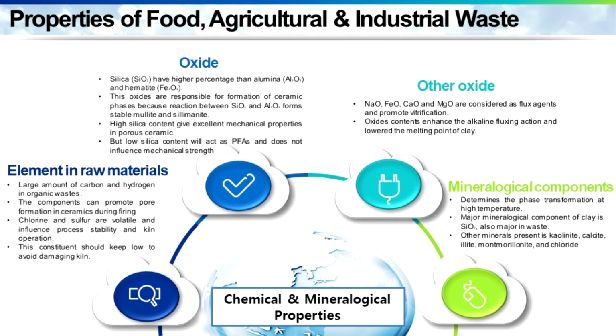For instance, the major silicon dioxide and aluminum oxide will contribute to the siliceous properties of the waste. These oxides are responsible for the formation of ceramic phases because the reactions between the silicon dioxide and aluminum oxide form stable mullite and sillimanite phases. These reactions result in porous ceramic with excellent compressive strength when the waste contains high silicon dioxide content.